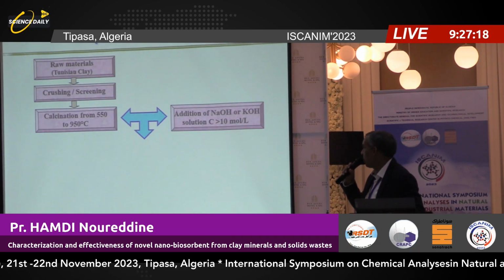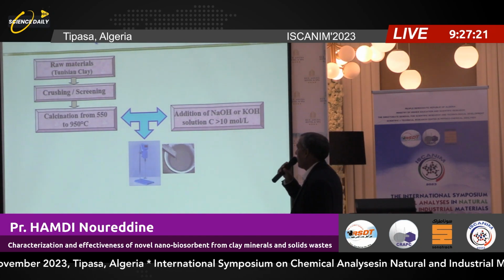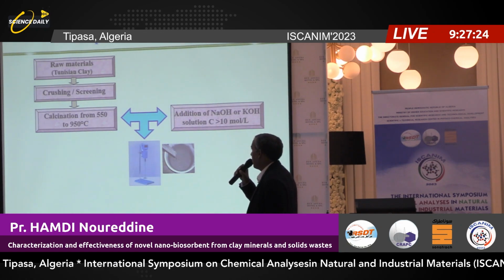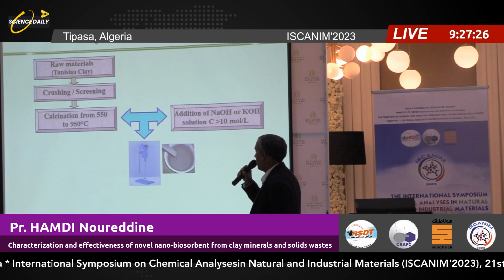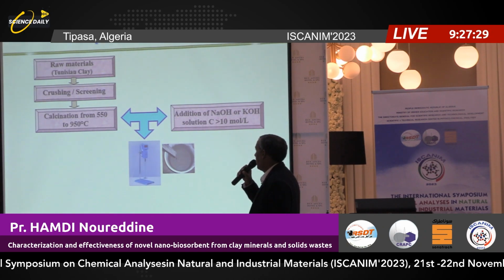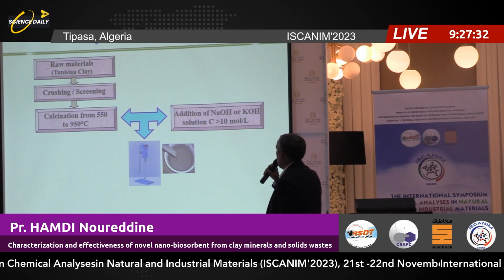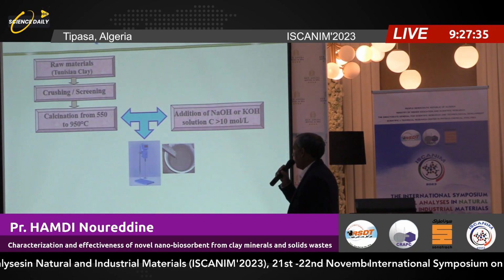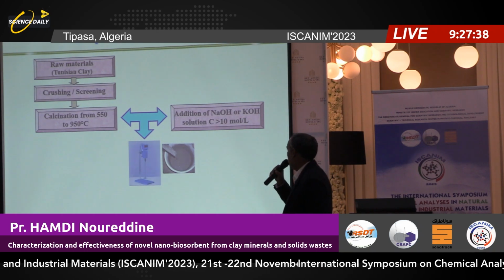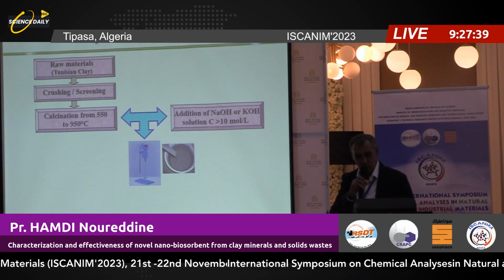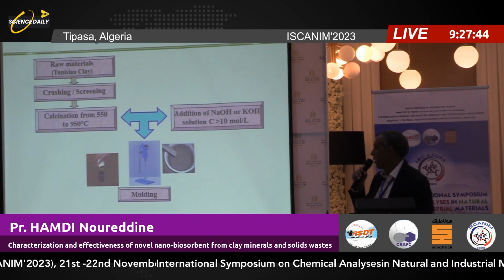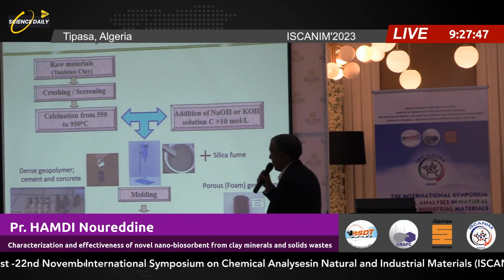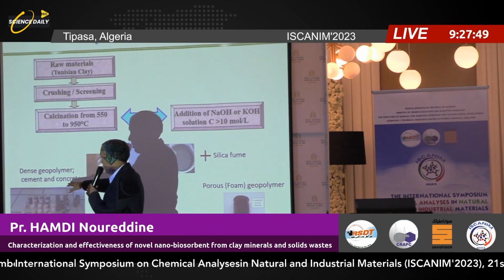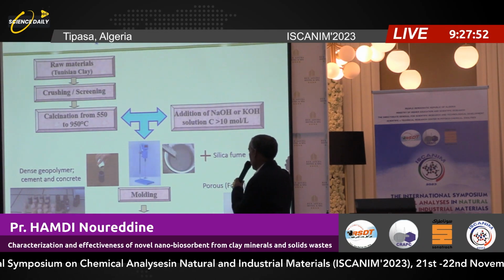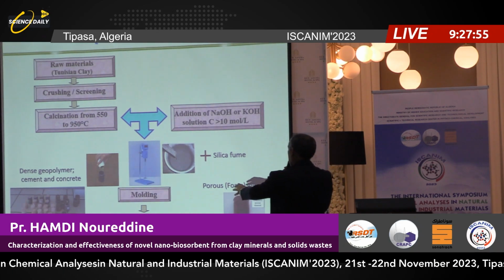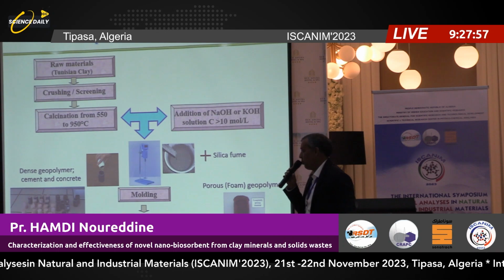Now to move to the preparation of geopolymer: first crushing and screening the clay mineral, after that calcination at high temperature, about 550 degrees C or 950 degrees C, then addition of sodium hydroxide or potassium hydroxide at a high concentration, more than 10 molar. After that, mixing, and we can prepare two types of geopolymer. The dense one is in general cement or concrete, but the second one is a very porous geopolymer, named foam geopolymer, when we add silica fume.